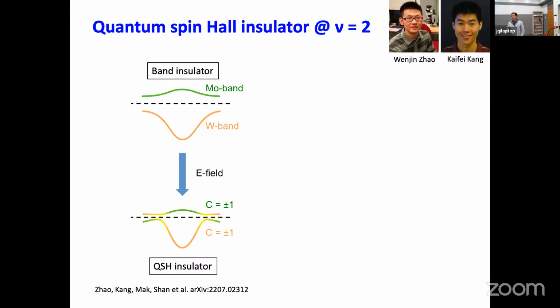So first of all, let me talk about something simpler. I'll look at filling factor equal to 2, meaning that we put 2 electrons per Moiré unit cell. We fix at that, and then we just tune the electric field in the system. What that means is that before band inversion, the Fermi energy, which is this dashed line here, is located between these 2 bands. Once you apply electric field, you may invert the band, but the Fermi energy is still located inside the band gap. Then you can turn the system from a band insulator to a quantum spin Hall insulator.